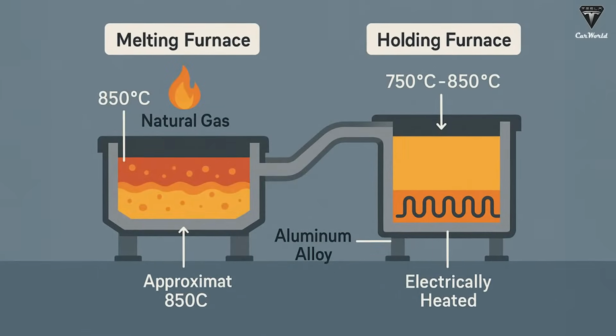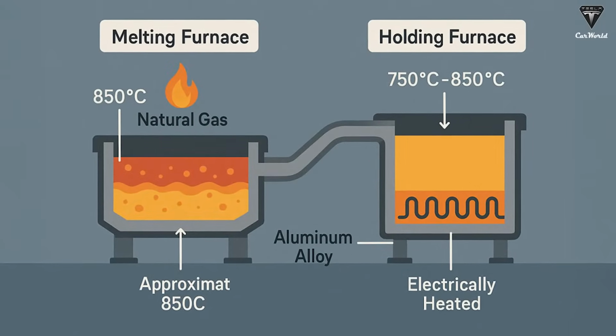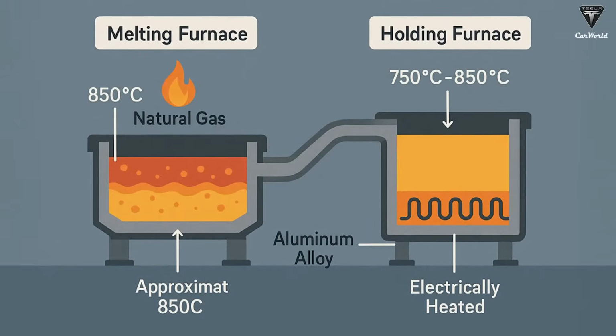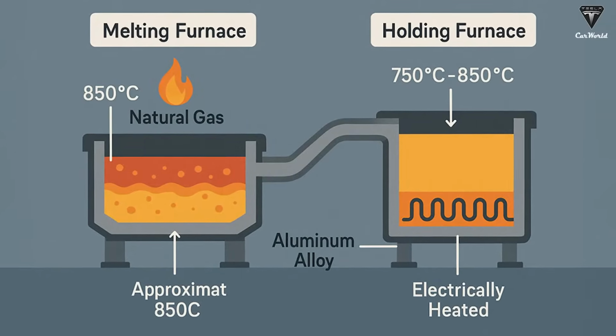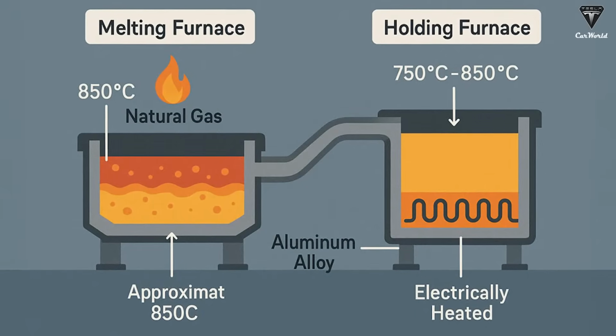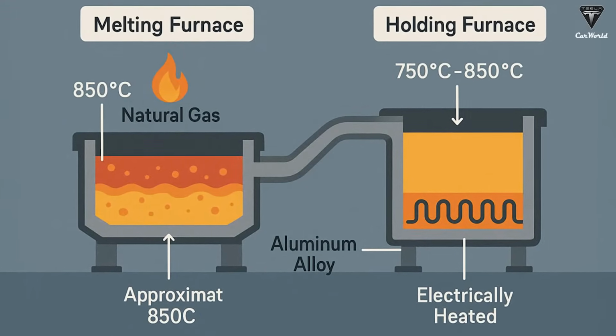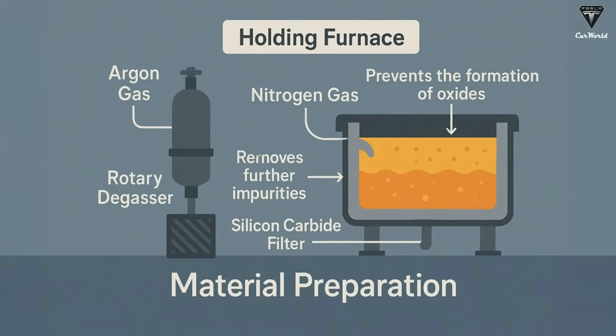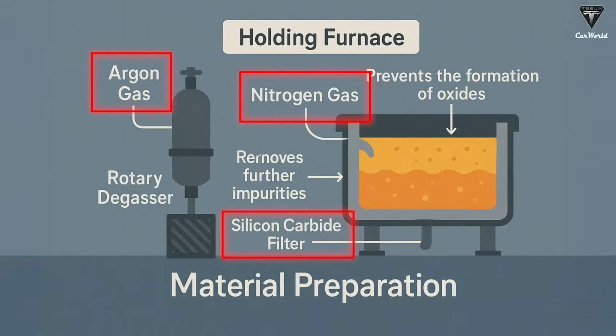The gigapress uses a 2-furnace system to handle the aluminum alloy. One furnace melts the aluminum, powered by natural gas, while the second furnace, heated electrically, keeps the molten metal at a consistent temperature for casting, as mentioned above. The interior of the holding furnace is filled with nitrogen gas, which helps prevent oxidation in the molten aluminum and maintains a stable temperature. Additionally, argon gas, a rotary degassing machine, and a silicon carbide filter are used to remove impurities and particles larger than 25 microns, ensuring the metal's high quality.